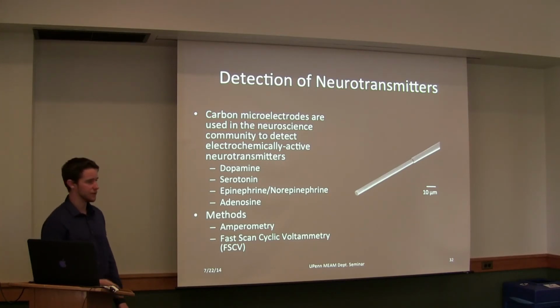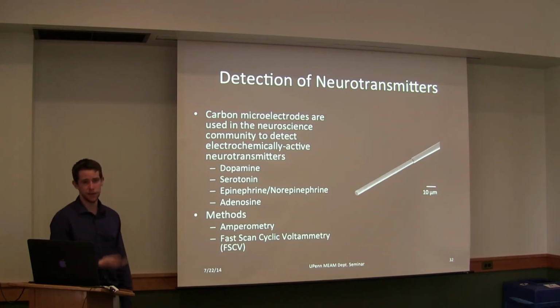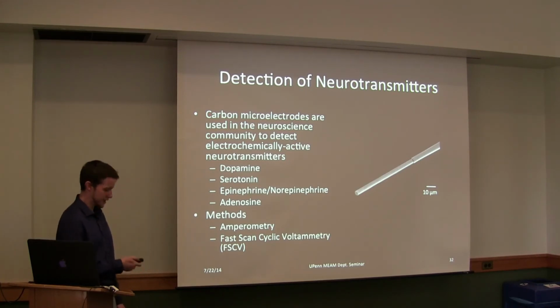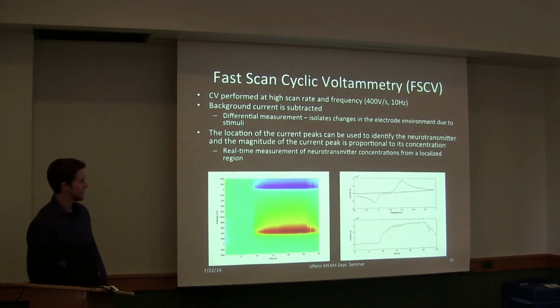Or fast scan cyclic voltammetry, where they apply cyclic voltammetry at a very fast rate to monitor these effects in real time. So to further elaborate, it's at a very high scan rate, we're talking about 400 volts per second, and they apply these triangle waves at a rate of about 10 hertz and measure the current response. And then they do a background subtraction to get rid of the capacitive charging currents that happen at high scan rates. What it gives you is a differential measurement that allows you to detect concentrations of neurotransmitters at a very high temporal and concentration resolution.